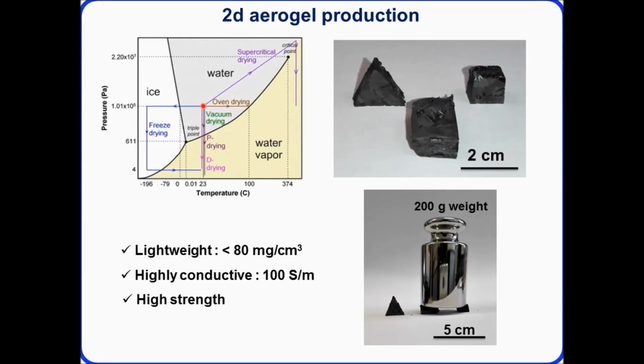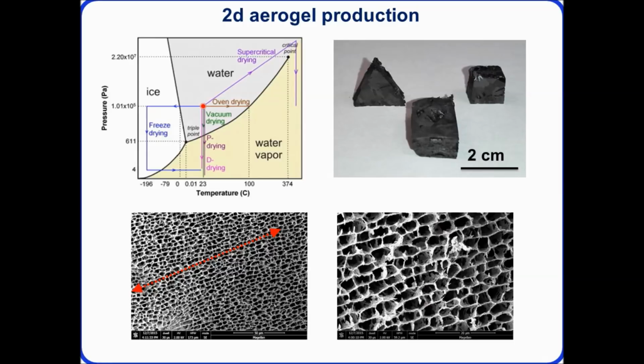So here are some of the typical structures that we make. These are now solid lumps. They're no longer an ink, but these are highly porous structures. They're lightweight, they are very low density, but they also maintain some conductivity because you have this framework of the conductive graphene, and they're relatively high strength as well. If you look under a scanning electron microscope, you can really see this liquid crystal orientation, this alignment, and this white area, these square shaped or column shaped structures are all the graphene that's left behind. So you're forming this nice sponge-like structure.